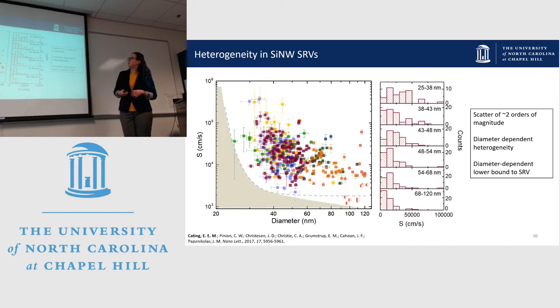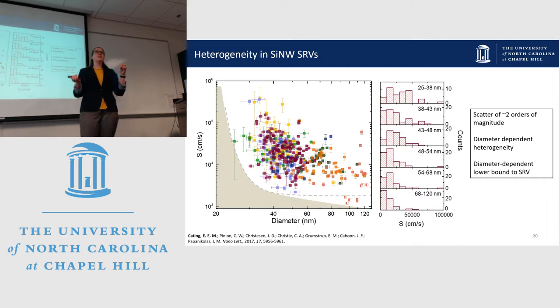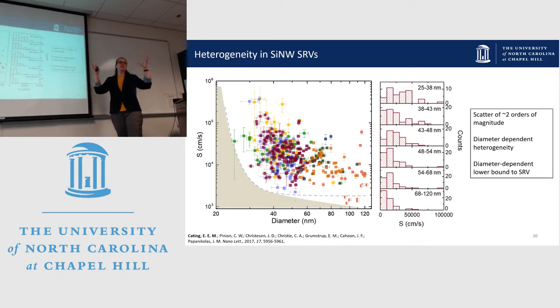The third thing that I'd like to point out is this trend that we see in the lowest measured surface recombination velocities. So again, a good surface has very few defects, which means it should have a very small surface recombination velocity. So the smallest one we measure represents the best quality surface that we found. And you can see that after about 40 nanometers, as your wire gets smaller, the best surface that we see tends to get worse, right? The recombination gets faster. So this means that if you want a really high quality surface, you probably want a wire that's a little bit on the larger side.